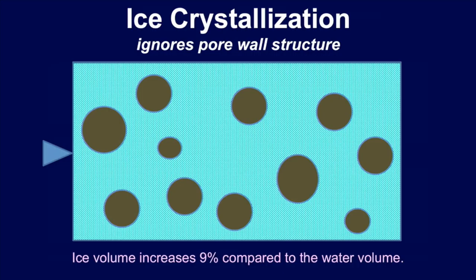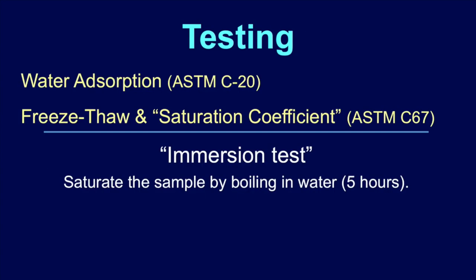That should change the way we think about freeze-thaw damage in outdoor sculpture bodies. It's not this idea of having lots of ice forming — you typically have one single crystal of ice that forms and then pushes through that material. Ice expands 9% by volume over water — everybody cites that, but my take is sort of 'so what.' The real issue is the crystal propagation.